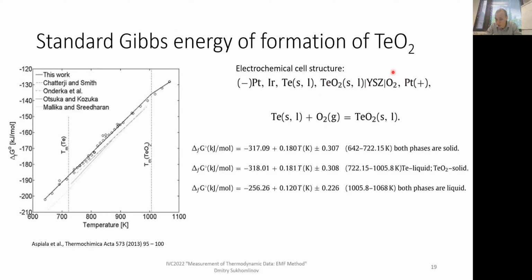Then the reference was selected to be pure oxygen gas. And here we have a virtual net cell reaction. Those vertical dashed lines show the melting points of tellurium and tellurium oxide. And then we have three different equations for Gibbs energy of formation for each range. So Gibbs energy is continuous, but because of this heat of fusion, the slope changes.